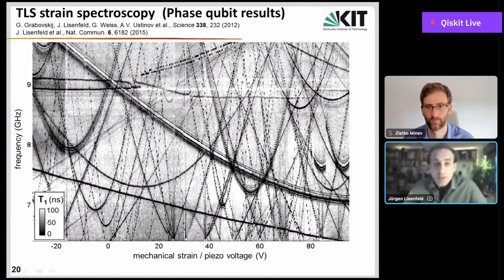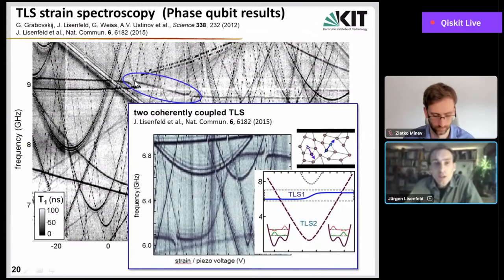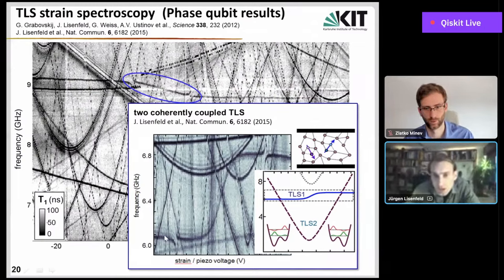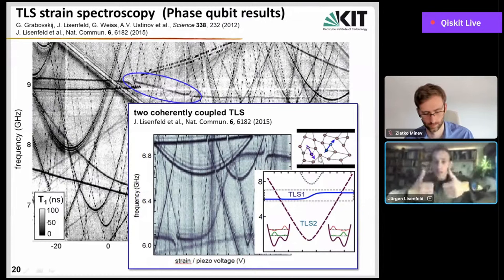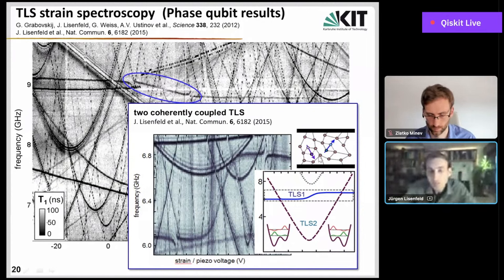I would like to point out that you often see some anomalies in these measurements, so non-hyperbolic traces. For example, one trace which looks suspicious is this one here, which is more like a horizontal line with some step function. At some point, we found such a signature again and studied it closer. You see that such a signature comes from two interacting defects. You may have just two TLS which are close enough to each other so that they can effectively interact by the electric dipole coupling.